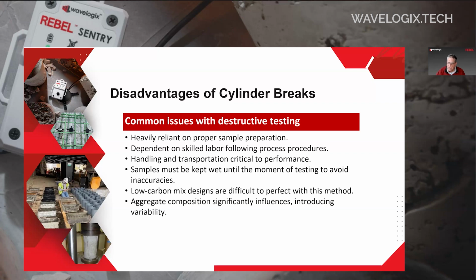And then once you get the samples demolded and brought to the lab, they typically have to be kept wet and wet right up to the moment of testing to avoid inaccuracies. And a lot of people take the samples, they store them in a water bath environment at a constant temperature of 70 degrees. And then they take them out, they might dry them off, and then they might crush them later, but they're supposed to continue to stay wet. So there's a lot of ways that technicians don't necessarily follow all the process procedures that are required by the specifications. And in doing so, you end up with inaccurate results.